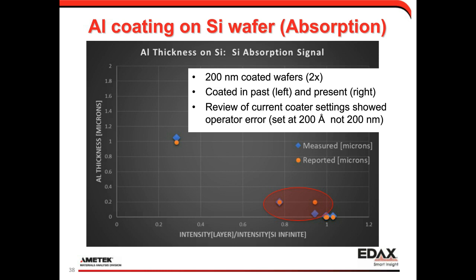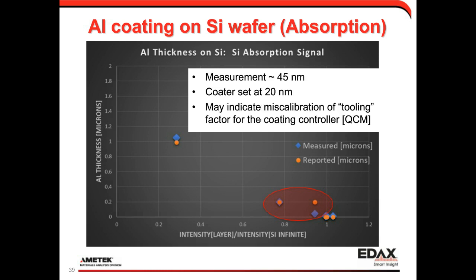The customer was reviewing procedures and processes, and he called me back later and told me the coater isn't set up for 200 nanometers now, it's set up for 200 angstroms. So he's really putting down about 20 nanometers of material when he thought he was putting down 200 nanometers. That's the primary source of error there. We're still measuring around 45 nanometers when the coater is set at 20 nanometers.